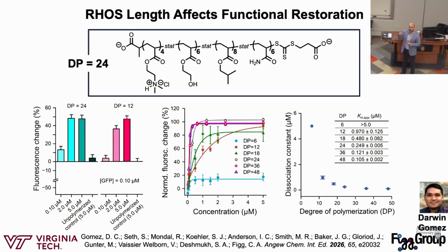We can look on average compositions and still see a functional output, which is really exciting to us. The data on the right is just showing that it's an effective length, which makes sense. So the fluorescence saturates around a DP of 24, so 24-mers. This is looking at apparent dissociation constants. Again, it plateaus around 24, and it doesn't get much higher than that. So all of this is saying is that we can actually have a pretty short polymer or oligomer where we can get fluorescence increases and pretty good dissociation constants.